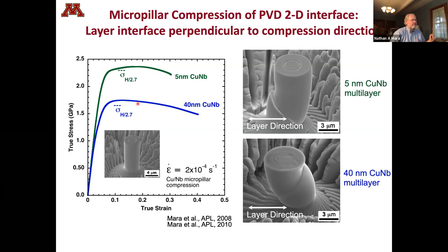Again, all that's in this is copper and niobium. We're not playing any tricks with alloying in this case. So this is just the power of those interfaces themselves. And what you see when you compress these afterwards is something that looks like this. So, yep, the pillar got shorter, it got fatter, but we have this shear band that has formed through the material. What we can do is take this back to the FIB, section it, and stick that in the TEM. This gives us some detail of what happened within this shear band.